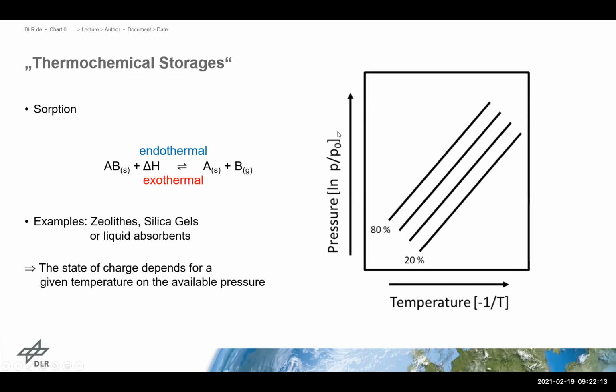It states that on the y-axis is the pressure, on the x-axis is the temperature. And if we assume we have a given pressure, we have several lines here. These lines correspond to the state of charge, or actually the coverage of the gas which is adsorbed on the surface of, for instance, our zeolite. And these lines state that, of course, if we increase the temperature for a given pressure, we can dry our surface. If we do not increase it that much, we have a larger coverage there. Or in other words, we talk about a gradual charging of these thermochemical systems based on sorption.